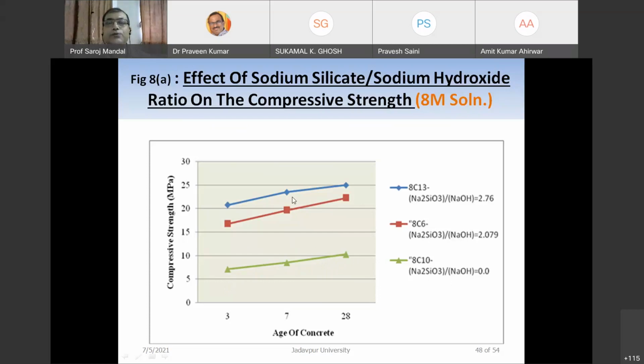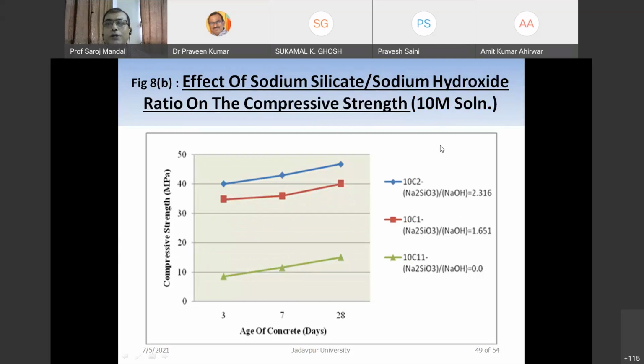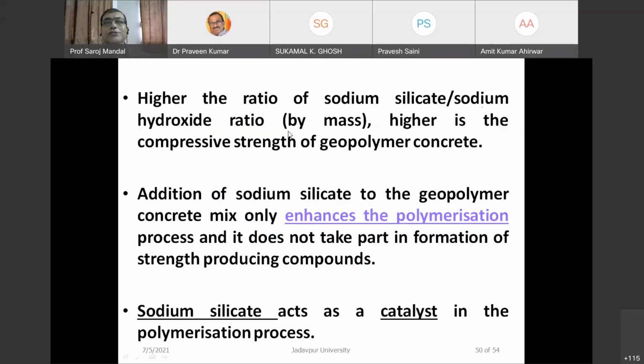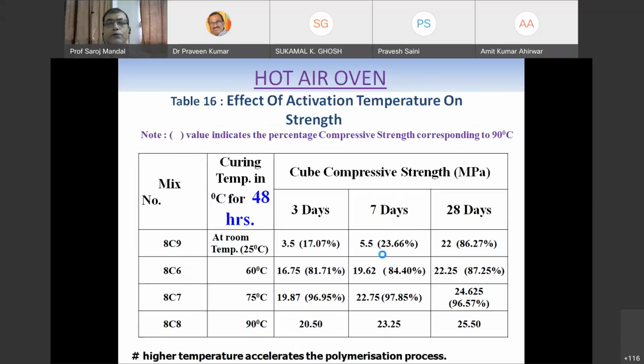So you see here that if we increase the amount of sodium silicate, keeping sodium hydroxide the same, from 0 to other values, at all ages your strength increases. This is shown here for 8 molar at all ages. I have also done it for 10 molar solutions, and it increases. So sodium silicate has a role, but it is not expressed in your reaction. It is estimated that it acts as a catalyst. So the higher the ratio of sodium silicate to sodium hydroxide, the higher the compressive strength of geopolymer concrete. Addition of sodium silicate to the geopolymer concrete mix only enhances the polymerization process and does not take part in formation of the strength producing compound. So sodium silicate acts as the catalyst in the polymerization process.